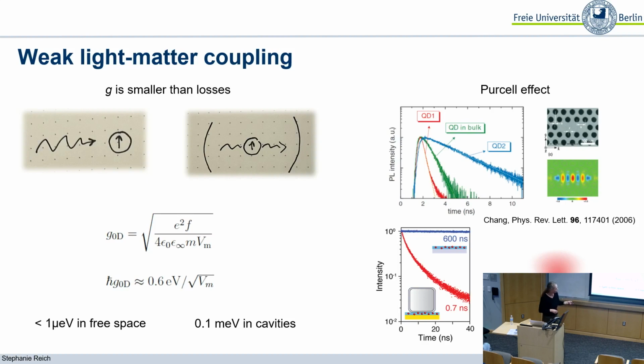And a very similar idea is shown down here. Here you have a thin film of molecules on top of a silver mirror. And here is the lifetime measurement again. So they have a lifetime of 600 nanoseconds. And then you take a cube, a metallic cube, and place it on top so that you make a cavity between the bottom layer of this cube and the substrate where the molecules are put on. And you can see that the lifetime of the emission decreases drastically to less than 1 nanosecond. And that comes from the increased light-matter interaction that you obtain thanks to reducing the mode volume here.